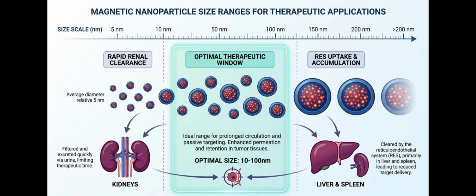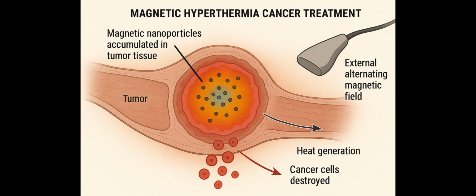However, an important point for real biomedical applications is that Brownian relaxation is largely suppressed inside the human body. Once nanoparticles enter dense environments such as intracellular compartments, which are endosomes and lysosomes, extracellular matrices, gels, or solid tumors, the fluid around them becomes too viscous or physically restrictive for the particles to rotate freely. As a result, Brownian rotation becomes strongly hindered, and Néel relaxation becomes the dominant heating mechanism during actual cancer treatment. This distinction is crucial because it means that nanoparticles must be engineered with their internal magnetic properties optimized for Néel relaxation if they are to remain effective once delivered into tumors.